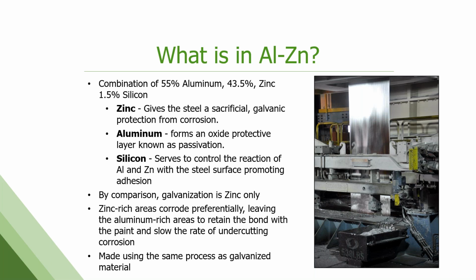Knowing that the density of aluminum is much, much different than zinc, it's a lot of aluminum by volume that's on this when it's finished, which is key to its performance. It's that aluminum component that's really giving it the superior corrosion protection. The silicon is in there mostly in the pot for wetting out and adhesion purposes. It doesn't really bring anything to the table once the product is finished.